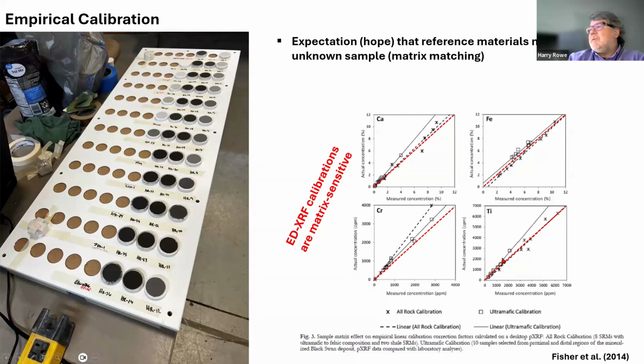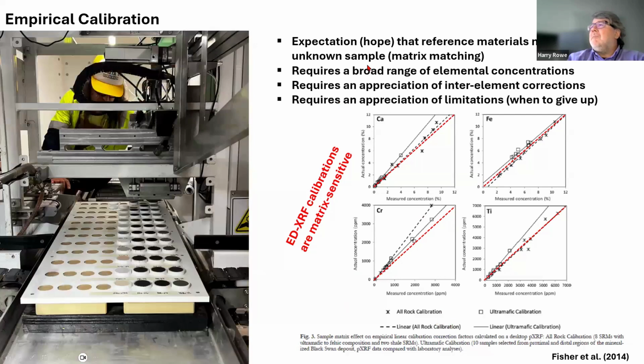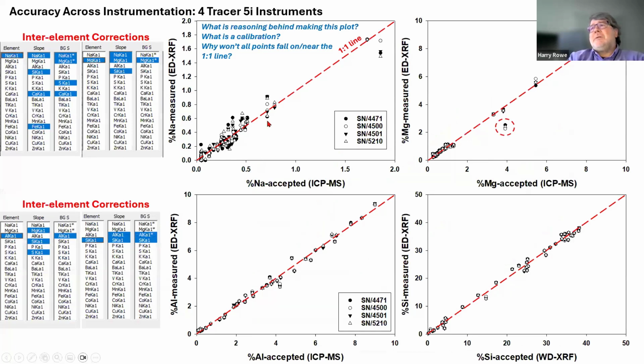But see the difference between these calibrations? That's the ultramafic, and this one is the all rock calibration. Highly variable, and if you notice, most of the time neither of these calibrations are actually on the 1-to-1 line, and that's something also that we look at. Getting a good calibration requires a good broad range of elemental concentrations, inter-element corrections knowledge, and an appreciation of the limitations. So this is our calibration, but it's our calibration on 4 instruments.